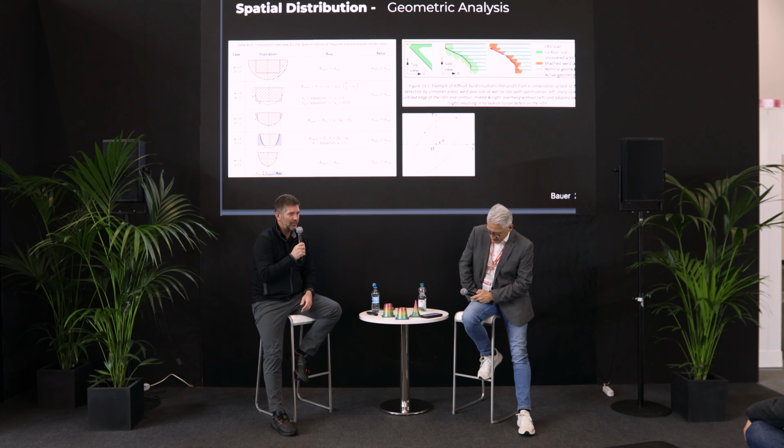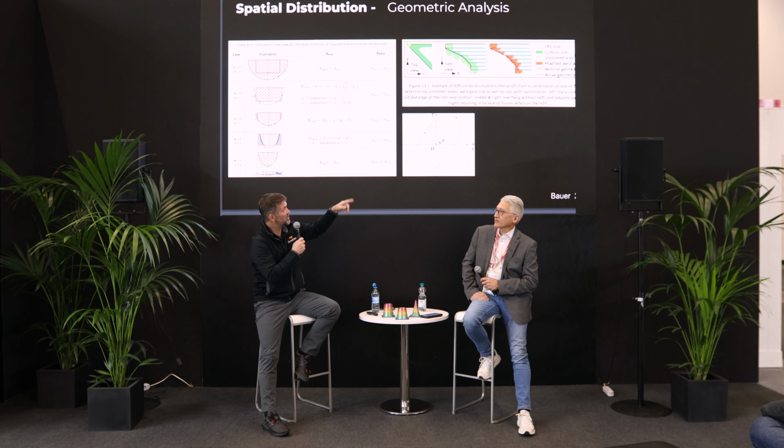First of all, the problem has become harder because there's now more degrees of freedom. That's great, right? However, we can now actually tailor larger melt pools, shallower melt pools, and have more design flexibility. So we can achieve this sort of strategy while maintaining productivity, because we can make larger, more stable, faster parameters, as well as some of these slower parameters that we might use near the surface to maintain feature resolution and surface finish.